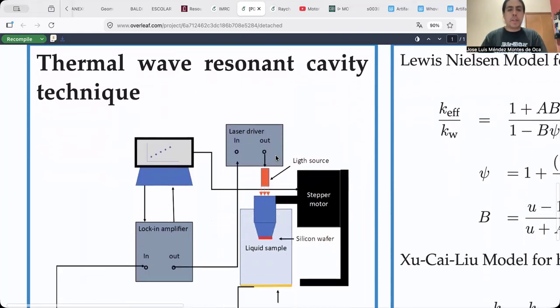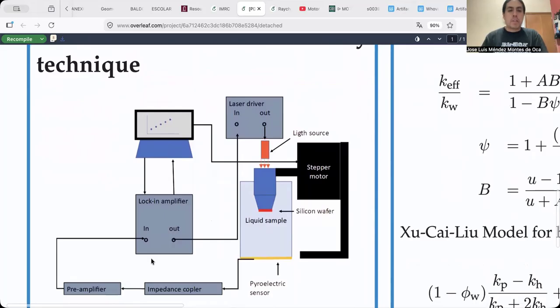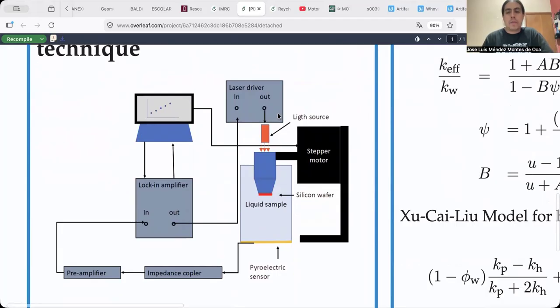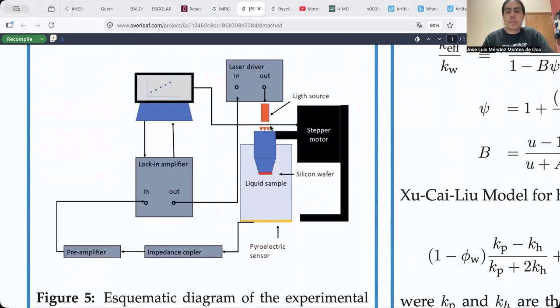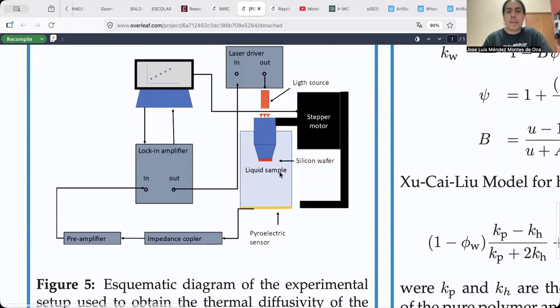And this is the experimental setup of this technique, which consists of a lock-in amplifier, where a sinusoidal signal is generated, called the reference signal, and this signal is sent to a laser driver to control the current for a laser diode, obtaining a laser light source with a given frequency and with a sinusoidal form. And that light is sent to a silicon wafer, which acts as a thermal wave generator by the photothermal effect.